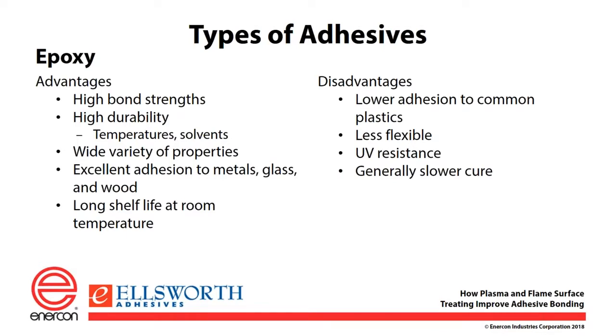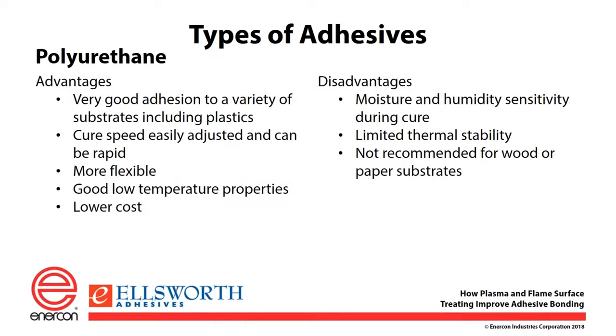There are disadvantages. They are used in the plastics industry, but they don't generally bond as well to plastic as some of the other adhesive choices. They're usually harder and less flexible, so they can cause you issues where you have two different substrates with different CTE values. In that case, you may not want to use an epoxy. You may want to look for a specially designed epoxy. They will discolor. If they're clear, you'll see them turn yellow with time, with UV exposure. They do that with heat as well. And they generally are slower curing than some of the other technologies.